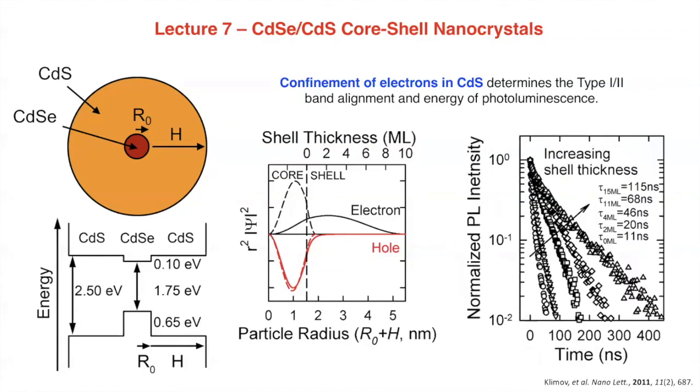The other thing that changes is the probability of the luminescence process, or the rate at which it happens. So people look at how quickly the photoluminescence intensity falls off with time to measure the lifetime of excited states in these materials. And what they find is that an excited state in a crystallite with a large cadmium sulfide region or a thick cadmium sulfide shell is quite a bit longer. So about 10 times longer compared to the core material that has no cadmium sulfide grown on it.